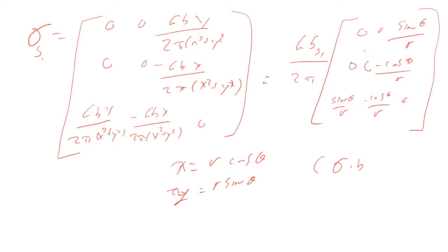this equation, sigma dot b cross L. Is this the Burgers vector for S2 or S1? S2, the one that is being acted on. And this L is also S2. And this is the stress field from S1. So we want to keep track of which terms belong to which dislocations. This is basically the force acting on the plane defined by the Burgers vector for S2. The Burgers vector for S2 acts in the z direction.